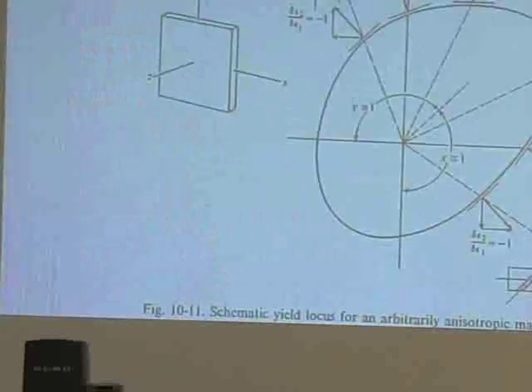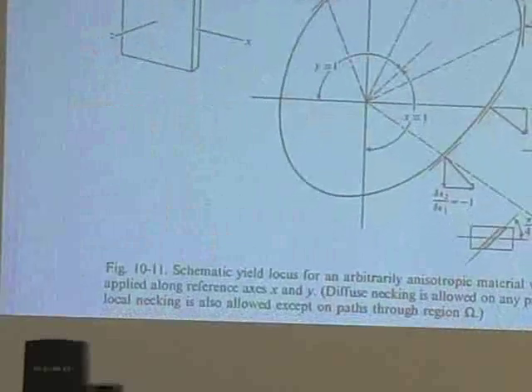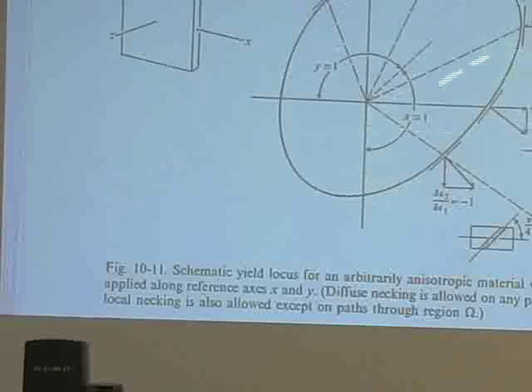And if you look at an arbitrary, this is out of Backofen if I remember, an arbitrary biaxial stress strain von Mises ellipse, not very elliptical, but Backofen wanted to point out it doesn't have to be. This is completely arbitrary. You will have regions, depending on whether you're in pure shear down here, going all the way up through plane strain here, over to another pure shear.